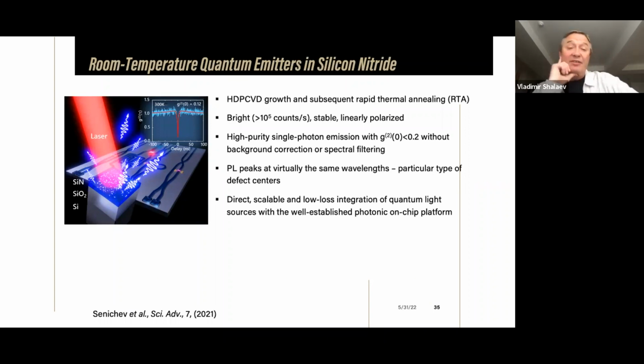So what we obtained recently is that in silicon nitride, which is a wonderful material used for nanophotonics, one can have very efficient single photon sources. For that, we actually use a slightly different way to prepare silicon nitride. Specifically, we use high density plasma CVD growth, followed by rapid thermal annealing. And it turns out this rapid thermal annealing is very important. As a result, we found that fluorescent background was strongly suppressed, so that you would be able to see many single photon emitters, which are bright with counts approaching, in many cases, a million counts per second, stable and linearly polarized. The purity of this single photon emission is quite high, routinely below 0.2, in many cases below 0.1.